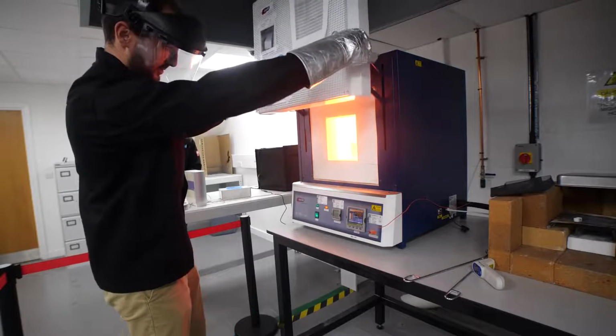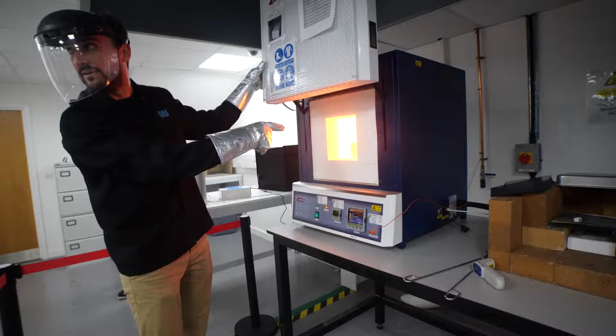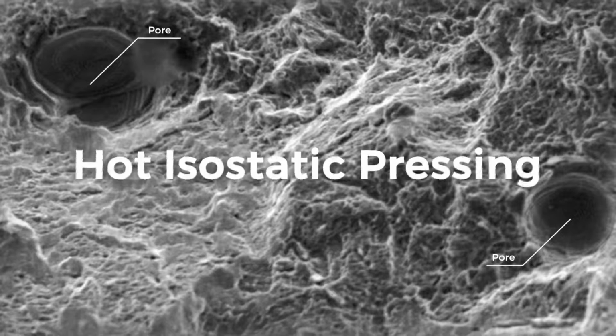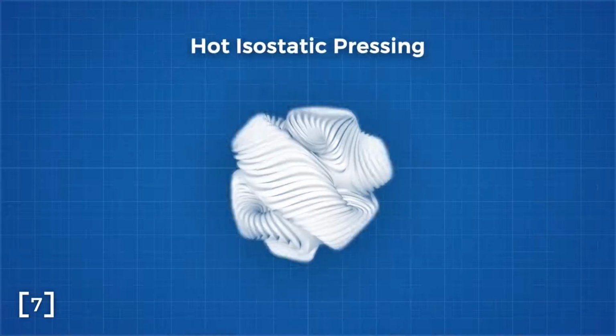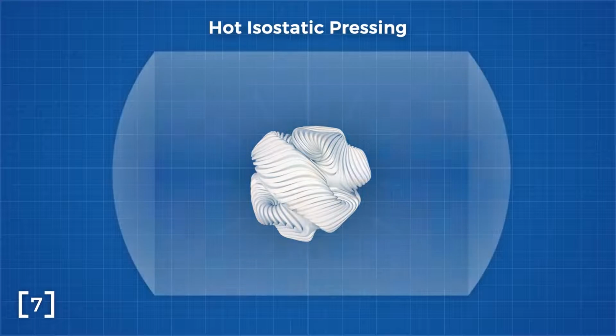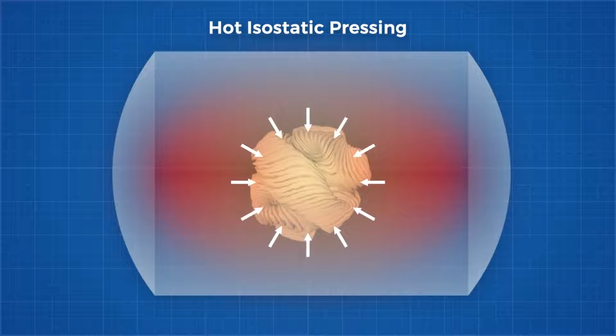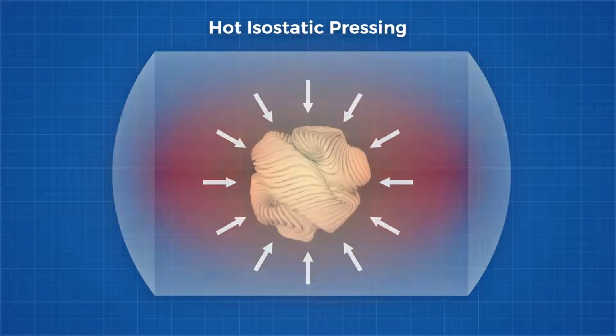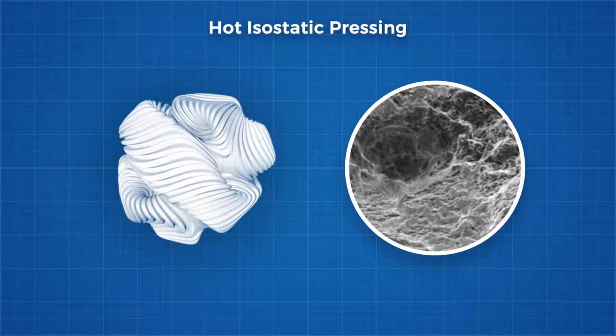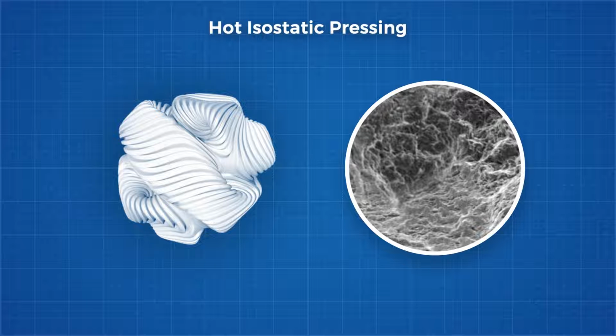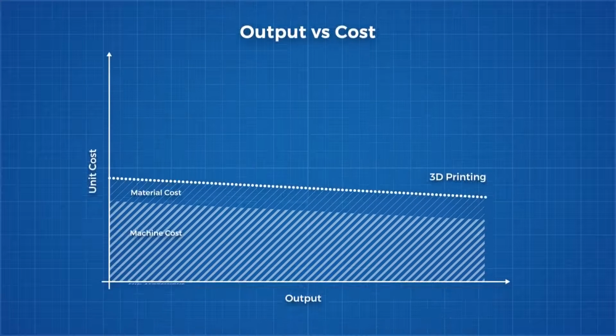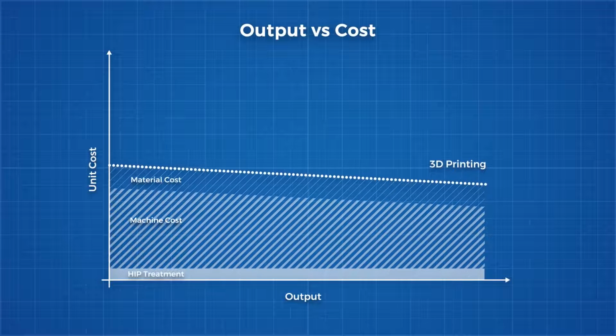Clearly, this process is much more complicated than just melting some metal powder together, and in the end, the final products that come directly out of a 3D printer are far from finished and need a significant amount of post-processing. For example, we can help close these pores by using a method called hot isostatic pressing, where we apply heat and very high isostatic pressure, which just means the pressure is the same in all directions. This maintains the overall part shape, but compresses and heats the part up enough to close those pores to improve our fatigue strength, but not enough to compete with traditionally machined parts. This, of course, pushes the cost bar higher, making 3D printing again less attractive for applications outside of rapid prototyping.